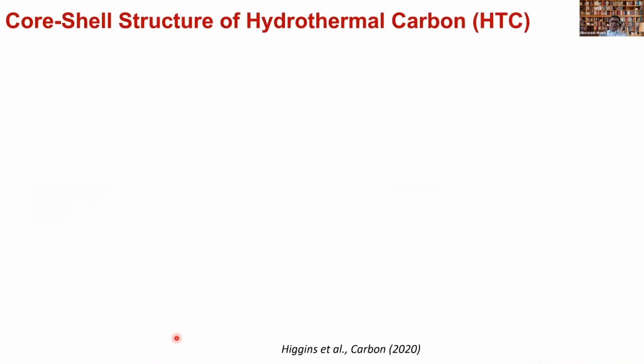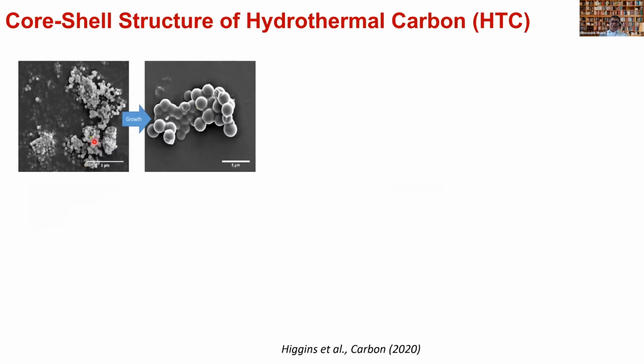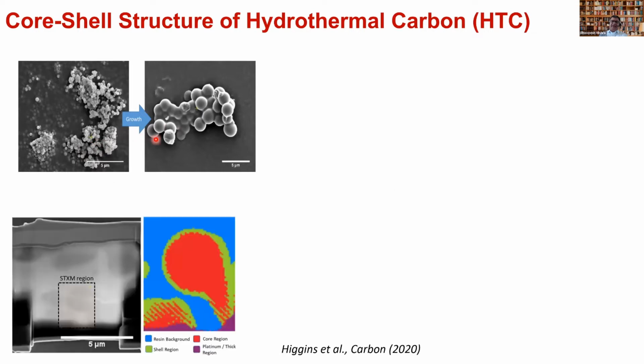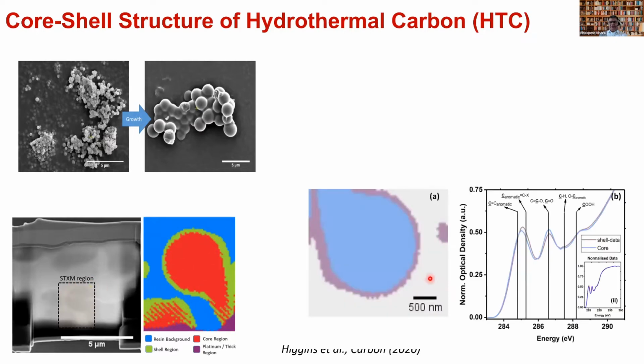So we used this method to try to resolve a long-standing problem in the carbon community, and that was the hydrothermal carbon. It was long thought that these hydrothermal carbons, which as you can see here grow from a small size to larger size as temperature grows, might actually have a core and shell structure. So we collected one of these, and then we did focused sectioning and took it to the diamond light source for STXM analysis. And this is the cluster analysis of that. And what we came up with is this beautiful core shell image. And if you extract the spectra from that, this is what you have.